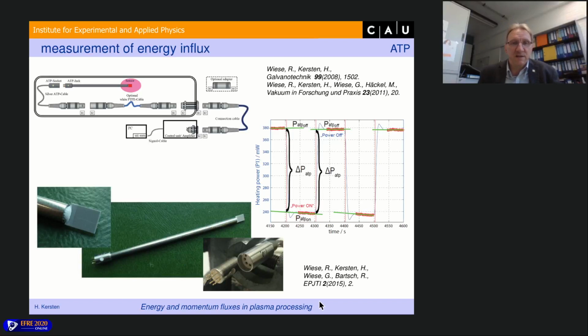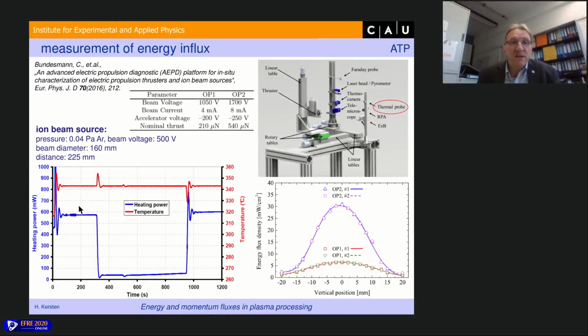I go to the next slide, better. Here you can see we heat, in this example, our probe to a temperature of about 340 centigrade, the red line, and we need for this temperature a heating power of our sensor of about 600 milliwatt. Okay, and now we switch on our plasma source, or in this case it was an ion beam source, and then in order to attain the same temperature, we just need much less heating power, only about 50 milliwatt now, because there is additional energy influx by the ion beam or by the plasma.